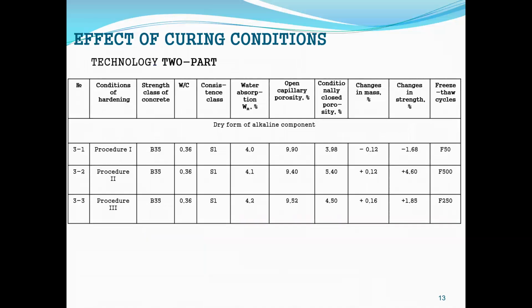Normal curing conditions of alkali-activated blast furnace cement concrete were more advisable if compared with curing in water or under steam curing in view of formation of effective porous structure. Porous structure of alkali-activated blast furnace cement concrete at consistency of class S4 and after hardening during 28 days under normal conditions was characterized by decreased volume of open capillary pores as well as by increased volume of conditionally closed pores compared with analogs under water or steam curing. Specified changes in porous structure contributed to formation of alkali-activated blast furnace cement concrete with more dense structure. This phenomenon provided advanced freeze-thaw resistance in contrast to analogs.